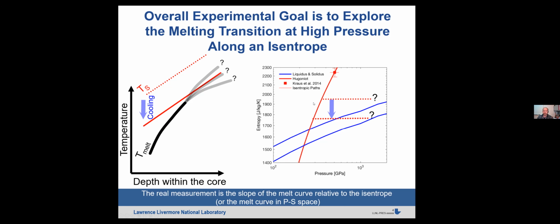And so again, thinking about that same thermodynamic space, we shock to a state on the Hugoniot, say at 270 GPa or 300 GPa, and then we shocklessly compress it to high pressures. So we isentropically or quasi-isentropically compress it to high pressures. So now in this space, it's a horizontal line, and then we pulse it with X-ray diffraction. So we can evaluate at this given point in pressure entropy space if we've solidified the material or not.